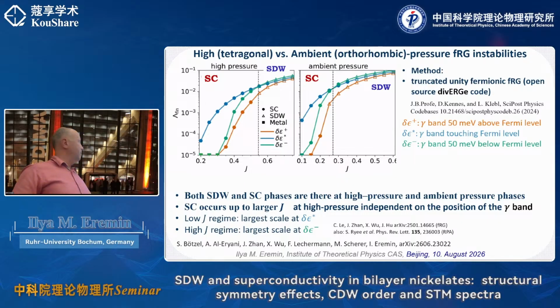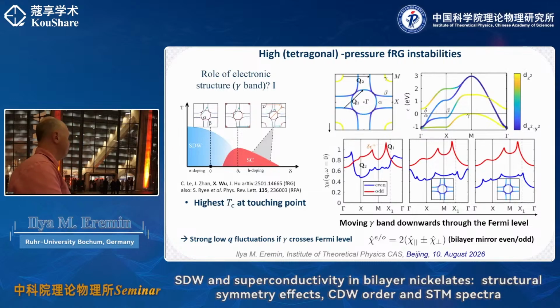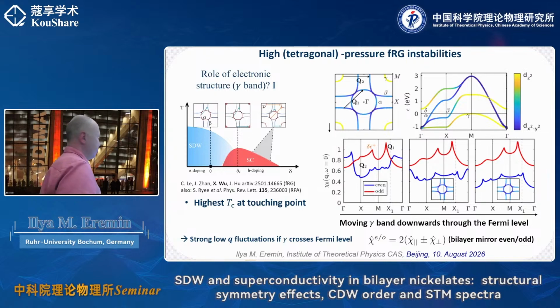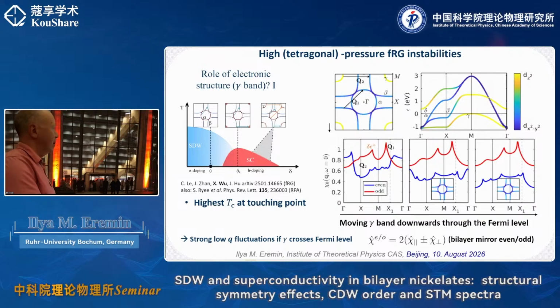And you see that despite this, let's say, different position of the gamma band, which by the way was very well understood by the previous works, which has been done here also, and also by the Hamburg group, the argument was that if you are for a moment only considering the tetragonal phase, what you see is that when there is no gamma pocket, then there is only one leading instability, and this is this pi over 2, pi over 2 instability, spin density wave. While if you introduce this gamma pocket, this further increases the magnetic susceptibility in the odd channel. That is the one which will be supporting the S plus minus. Once this gamma pocket gets too large, then you basically suppress superconductivity, and this is where the curve will go down. So that's what happens in the purely tetragonal case.